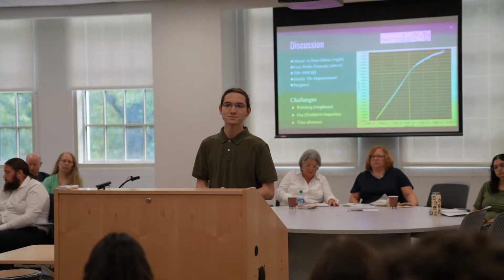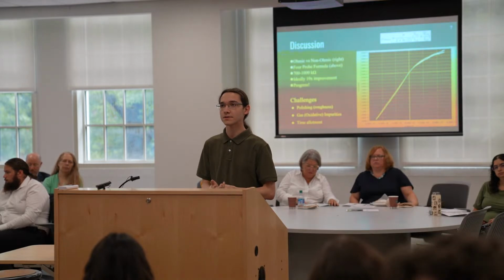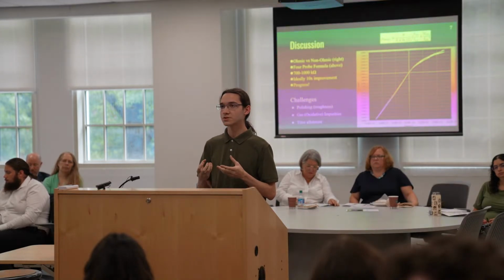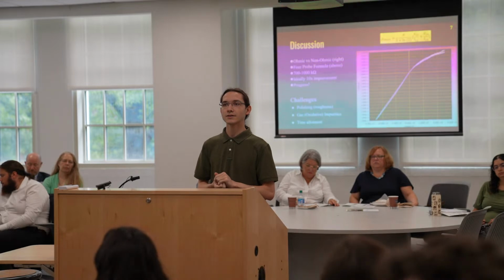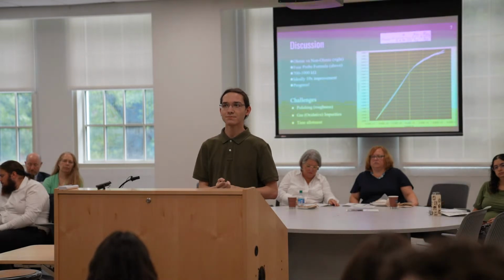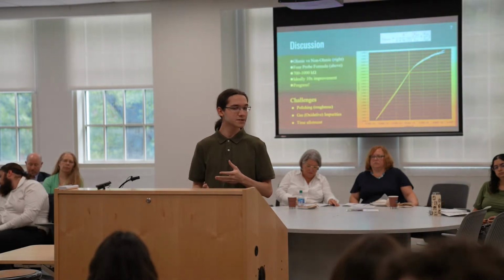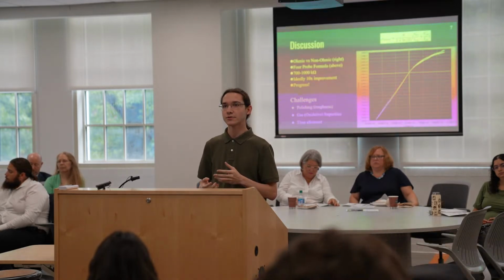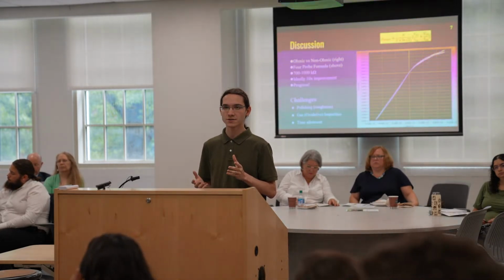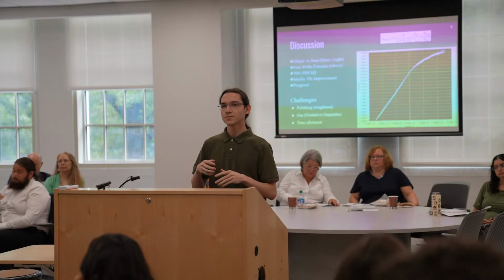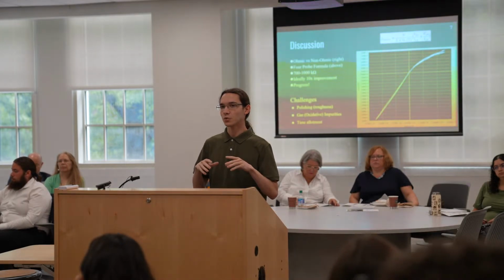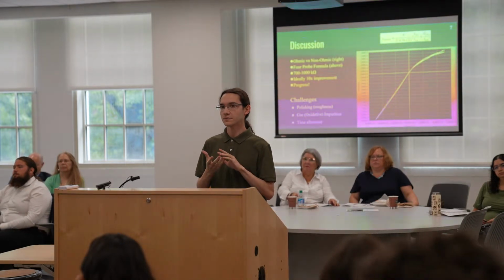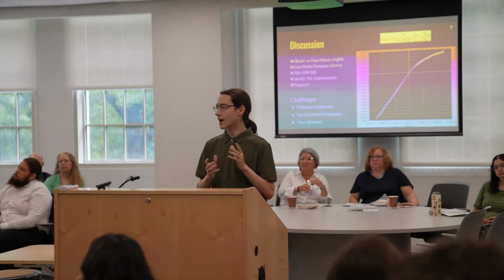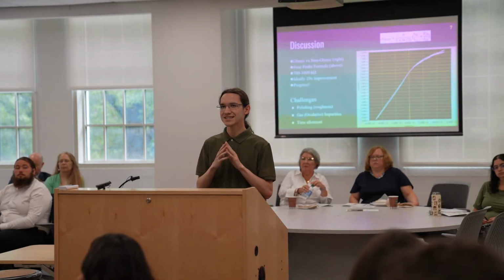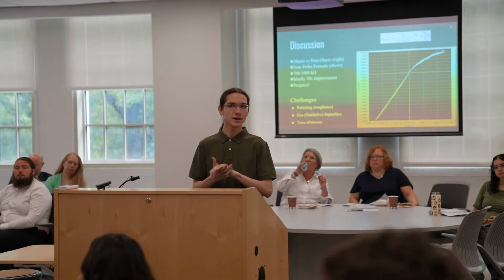We were successful. For our 4-probe method, we wanted more concrete values, and we used the formula pictured at the top there to get values for sheet resistance, which for some of our best data was in the range of about 700 to 1,000 kiloohms. Ideally, we're about an order of magnitude off of some of the best data. Best published data is around 70 to 100 kiloohms.